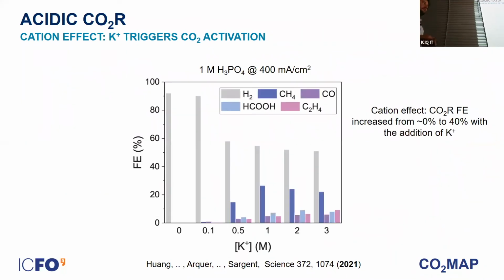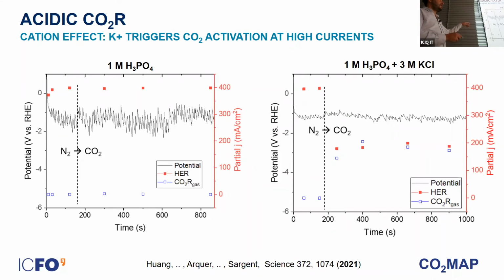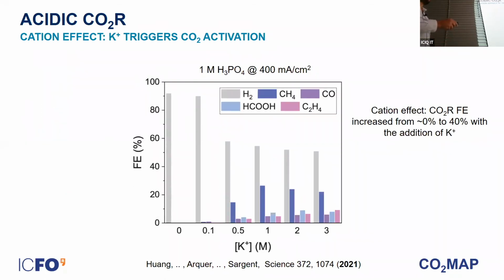Okay. Just to study this more broadly, we changed the amount of cations in the system for a given buffer solution and for a given current density, in this case 400 milliamps per square centimeter. Importantly, if we did this at lower current densities, not at 400 but at 200 or 100, in the regime where we were still taking the protons from hydronium, this effect was not so prominent. Only when you operate at a high enough current density that the surface pH is above a certain threshold is this cation effect prominent. You can see here, we start adding some potassium to the system, and we can then start identifying some methane, some carbon monoxide, and even some ethylene as we increase the amount of potassium.